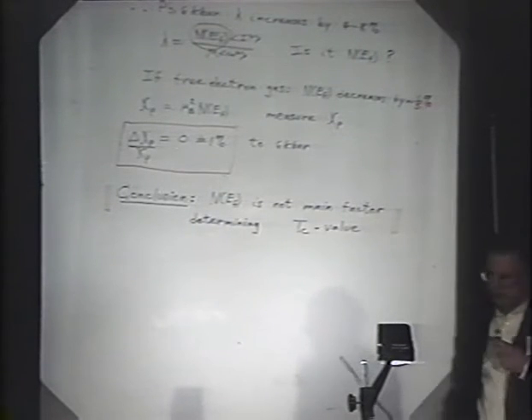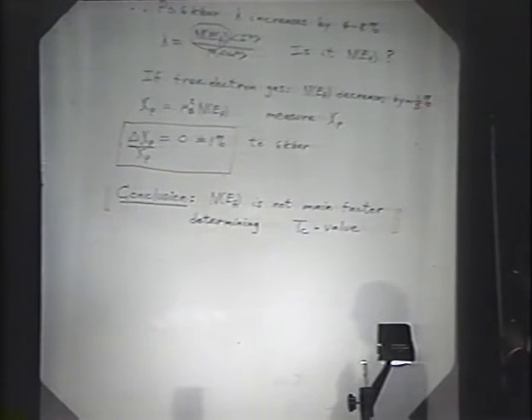So the conclusion is that for the pressure dependence of TC, the density of states does not appear to be the driving factor. And we've heard this before. If you go from the strontium compound to the yttrium barium compounds, the density of states goes down a bit, but TC goes up by a factor of 2. So it doesn't appear to be terribly important.